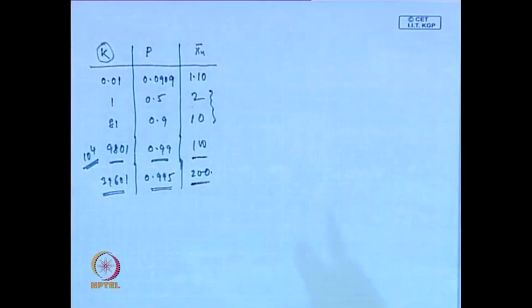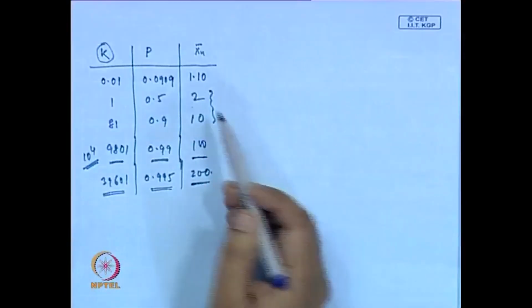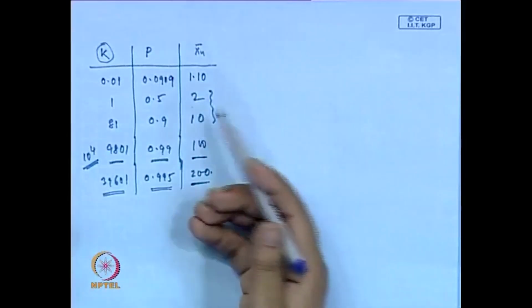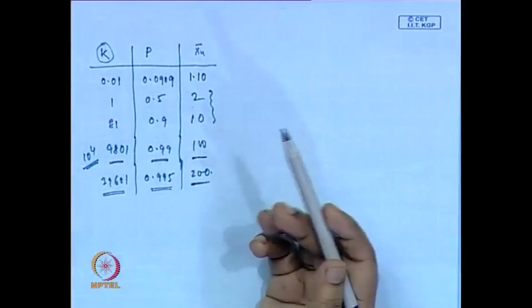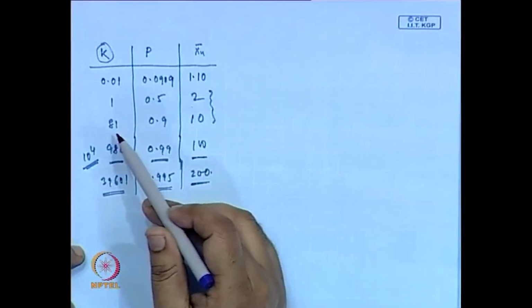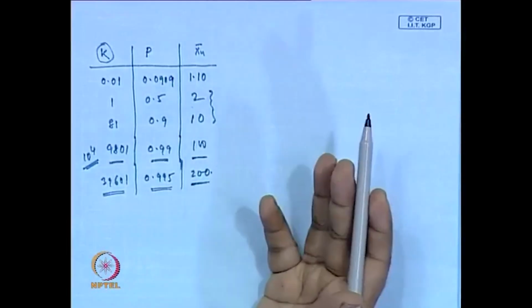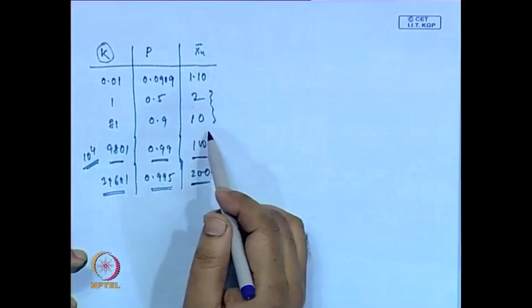If you do not remove your condensate, then your reaction will end up at an oligomer stage, maybe dimer, trimer or tetramer, a mixture of those, but the average will be a dimer for an equilibrium constant of 1, and for an equilibrium constant of the order of 10 to the power 2, it will be at xn about 10.